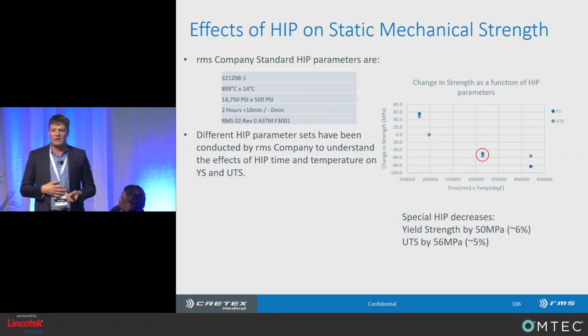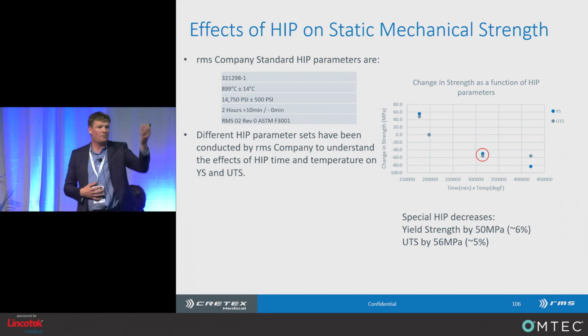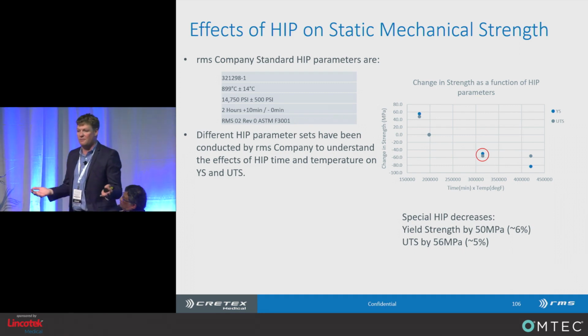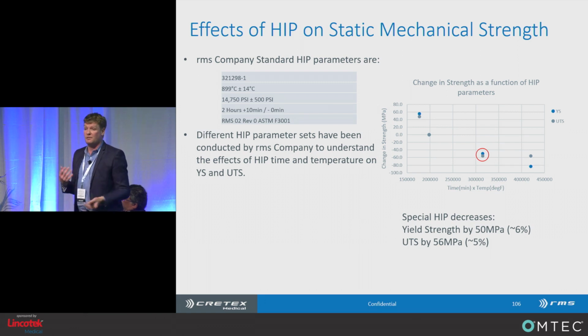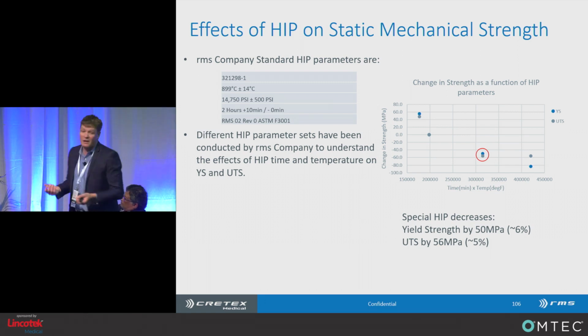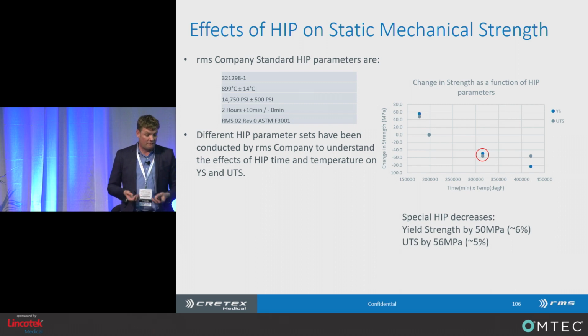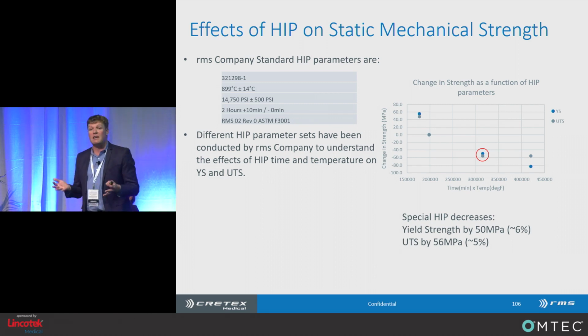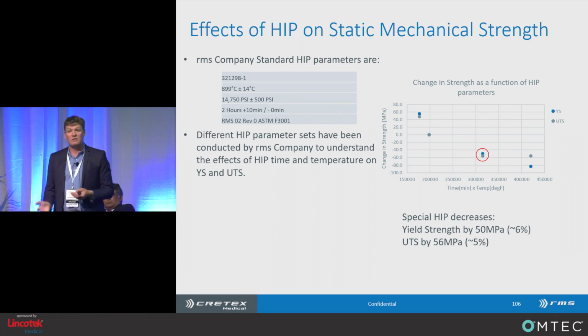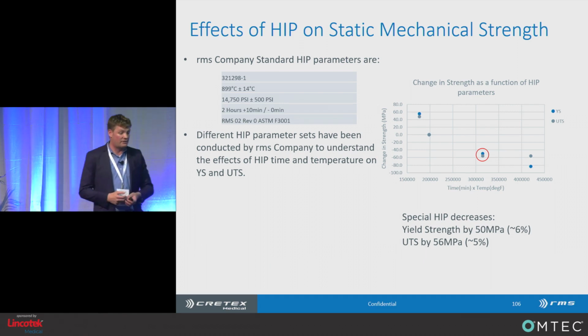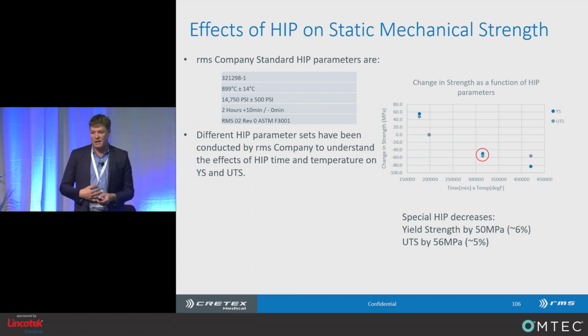I did some studies where Quintus helped me out with a couple of these studies, and a couple of my other vendors, where we did hot isostatically press parts at different times and temperatures. And what we saw is that we can get upwards of 50 or 60 MPa variation in yield and tensile strength performance, depending on what we use for hipping parameters, right?